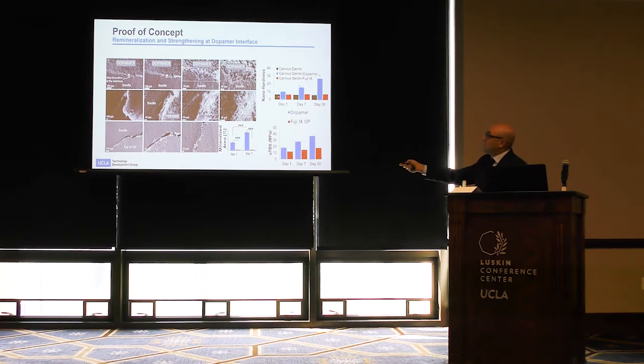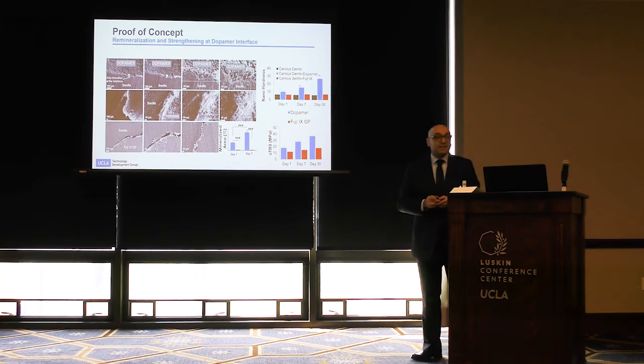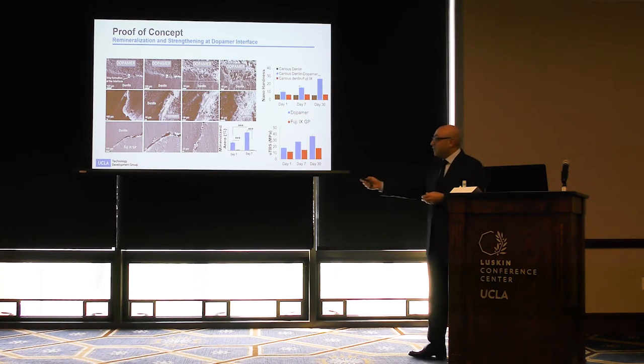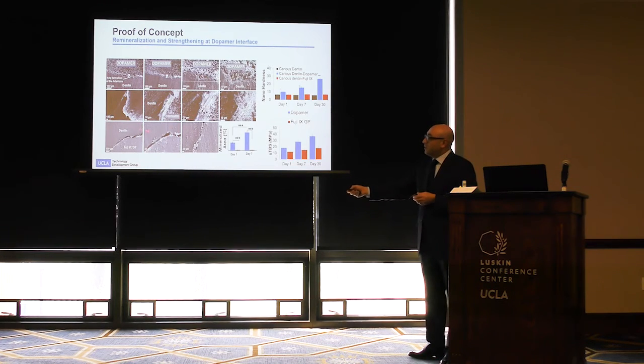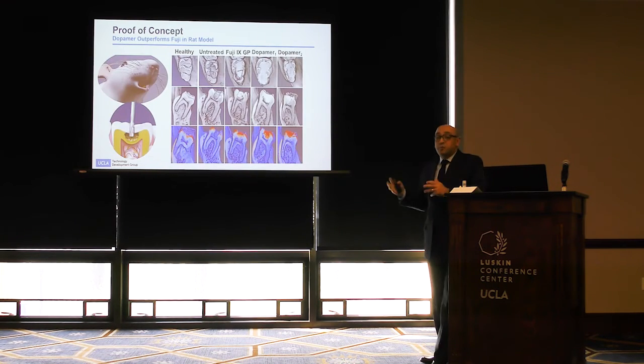As you can see here, from day 1 to day 30, whenever we have Dopamer adjacent to the caries dentin, there's a significant increase in the mechanical properties. Versus our commercially available product, we don't see that, and we see that there is still a gap. So basically, these results were very promising for us.